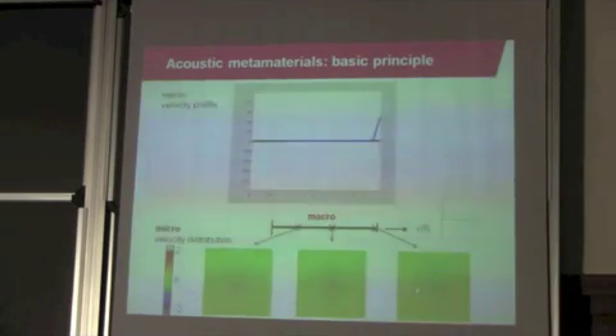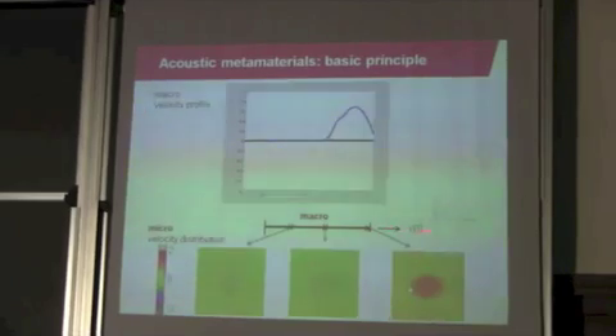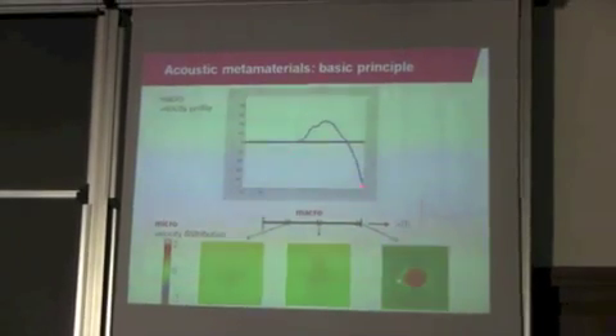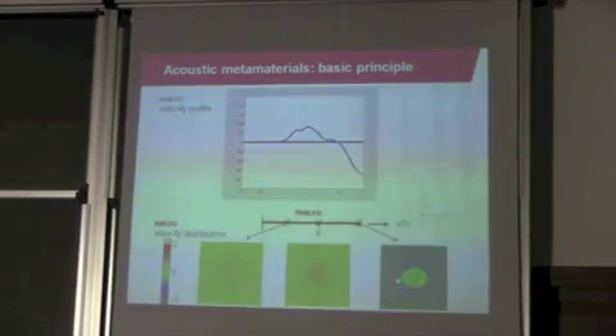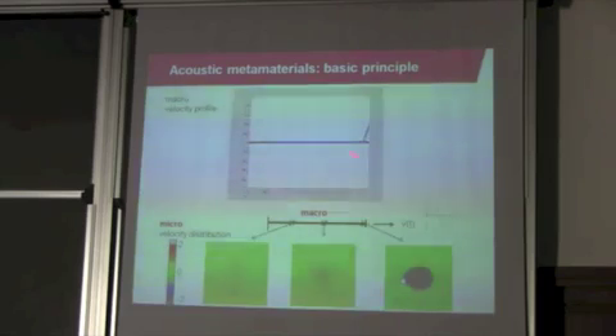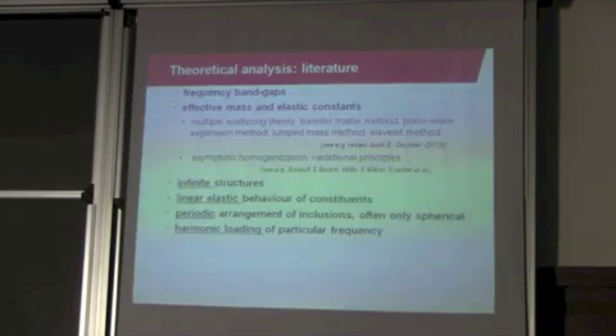Just to give you an idea how this works, this is a simple illustration. You have a rod made of this material, excited by a pulse. This is the wave propagating through this material, which attenuates pretty quickly. And this is what is going on in the microstructure that leads to this attenuation. The red and blue colors correspond to positive and negative velocity. You can clearly see that at a certain moment, the wave in the epoxy and in the particle are out of phase, and that local resonance effect attenuates the wave. By the time the wave comes to the other end of the rod, there is not much left to be attenuated anymore. Okay, so that's the material we are looking at.